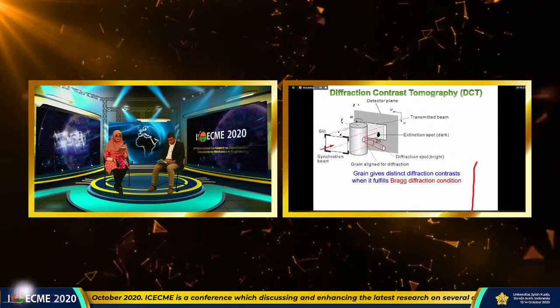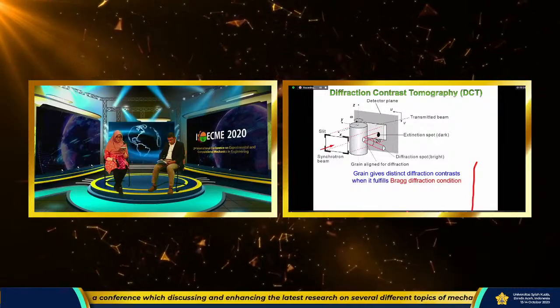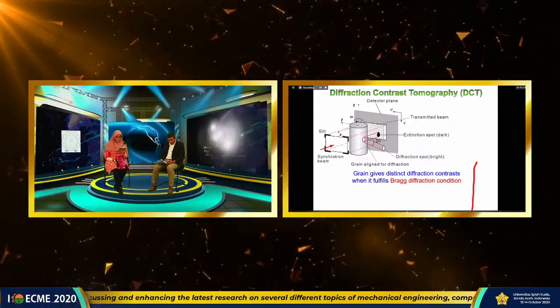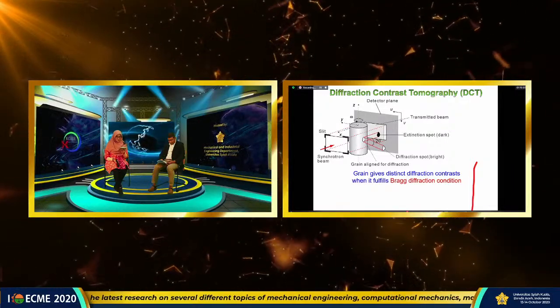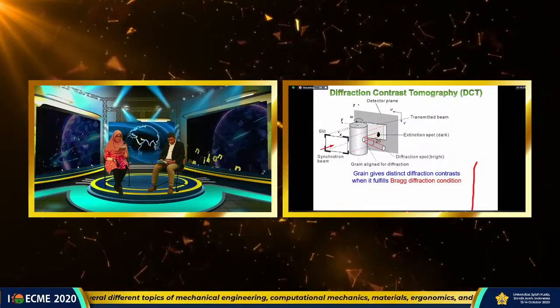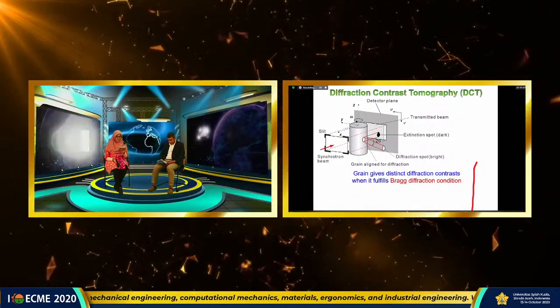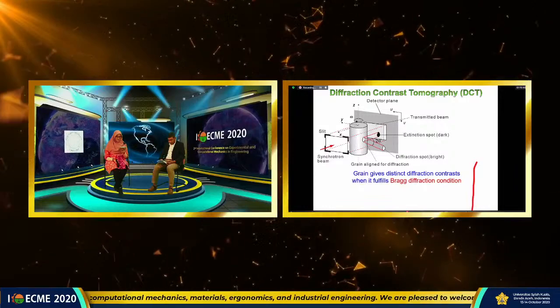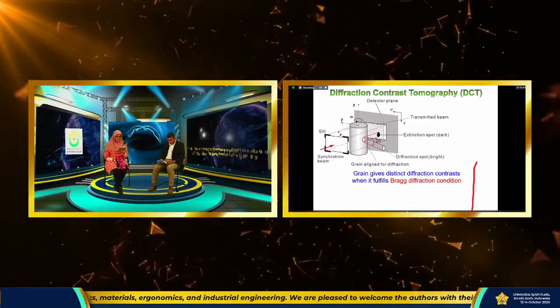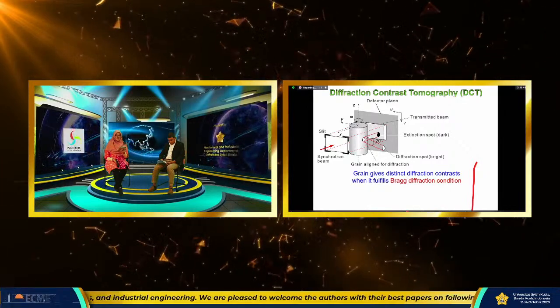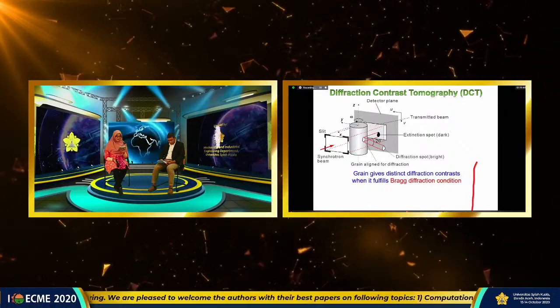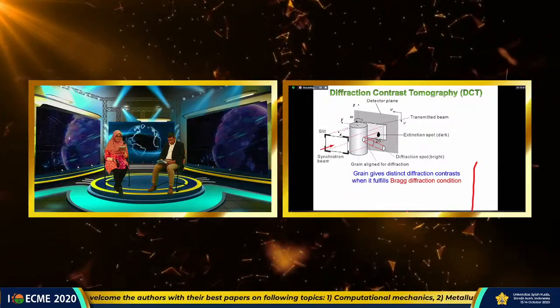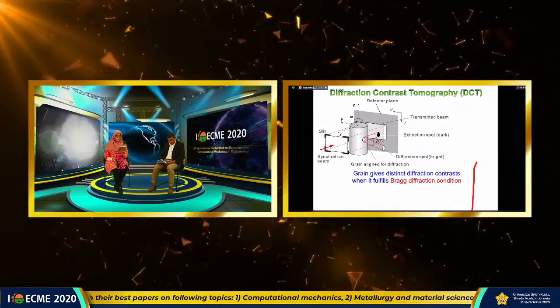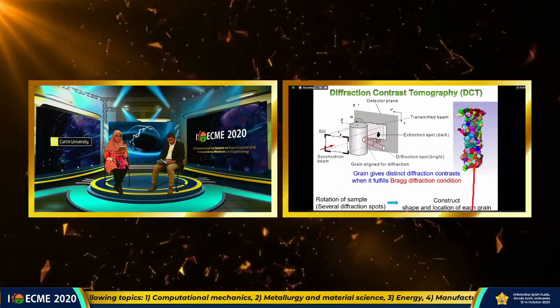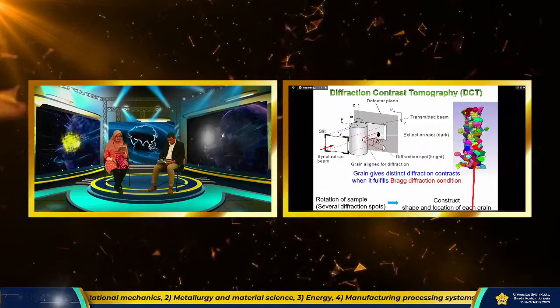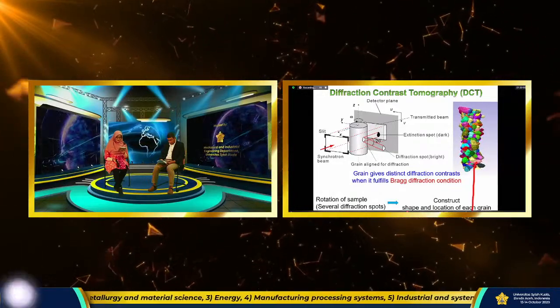If the grain has no misorientation, I mean the diffraction plane is perfectly flat, the shapes of the diffraction spot and its extinction spot correspond to the projection of the grain from the incident X-ray direction. Then the three-dimensional shape and location of each grain can be reconstructed by classifying the spots into groups belonging to individual grains. This is a result of this diffraction tomography.